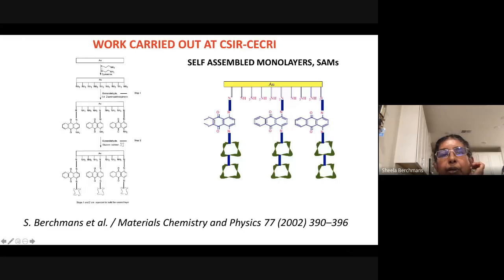So this slide talks about the incorporation of a mediator and glucose oxidase to cysteamine monolayer. Cysteamine monolayer, it is amino ethane thiol. So to the cysteamine monolayer, we have incorporated the 1,4-diamino anthraquinone. Diamino anthraquinone, which is a mediator, is attached covalently to this thiol molecule, which is then covalently linked by glutaraldehyde linkage to glucose oxidase.